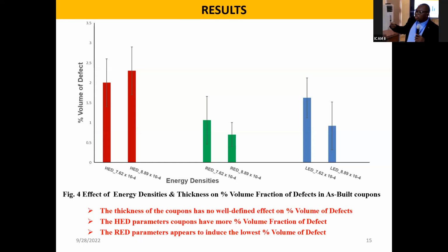So, quantify is part of what I've reported in the first illustration. I quantified the volume fraction of this defect using image analysis. And I found out that, irrespective of the material, the recommended energy density actually produces the lowest defect, while the higher energy density is higher, and even the lower energy density is higher. So the difference appears, because one is not consistent, the other is not consistent.